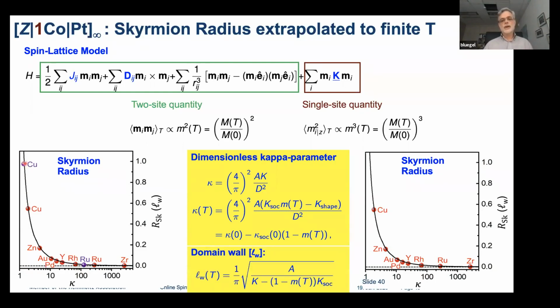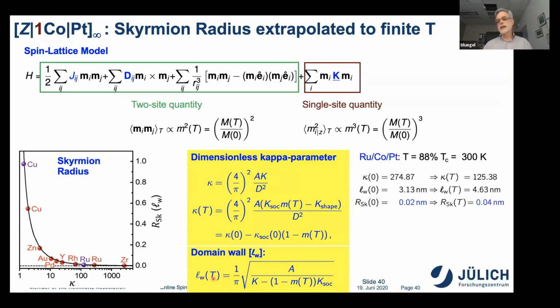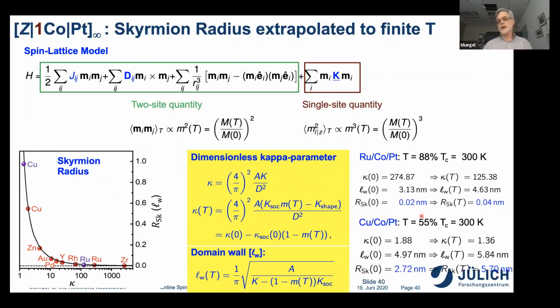And if you include now also the domain wall, which becomes also larger at smaller, finite temperature, you see that, for example, for copper, the copper cobalt platinum system, the skyrmion radius changes from 2.7 to 5 nanometers. This is basically a little bit more than factor 2 over room temperature.